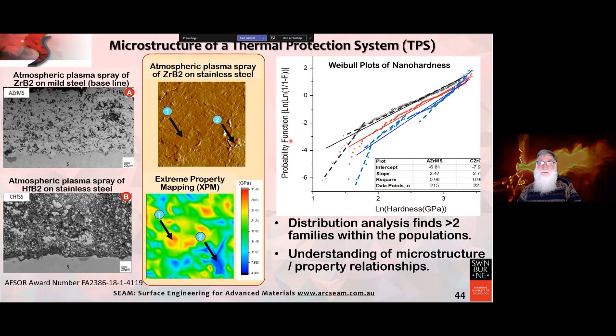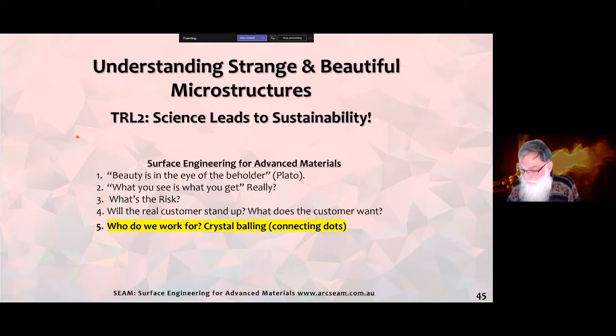We carry out a probability distribution function analysis via a Weibull, and we determine that there are different families of phase constituents composed within this complex microstructure. And we are attempting, by varying the thermal spray conditions, to maximize these high hardness regions. So again, let's get back to the theme. These are ugly microstructures. However, the functionality for a TPS is extremely demanding, and the ugly microstructure is proving to be quite successful. I have another 5 slides, Mr. Chairman, I believe. So we're getting towards the end here.